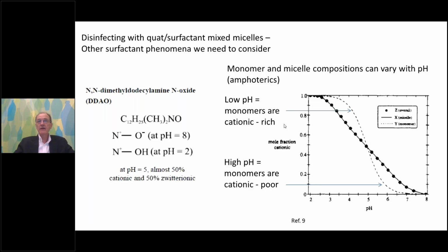Well, we're going to blend our quat with something else. If we select a co-surfactant like an amine oxide, we need to think about the actual mixed micelle composition as a function of pH, because it's amphoteric. Amine oxides at low pH can exist as totally protonated cationic form, and at high pH they're in their zwitterionic form. And so what we have in the plot is a mole fraction of cationic molecules for both the monomer and the micelle as a function of pH for this particular co-surfactant we might pick.